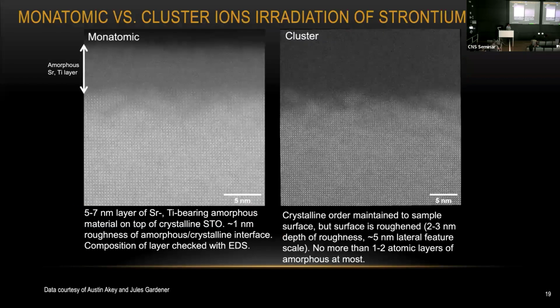And here's some data taken from my colleagues Austin and Drew. Both of them are not here today. They are working on strontium titanate, and it's a single crystal chip. The sample size is almost 1 centimeter by 1 centimeter. The main difference between these two measurements is that for one piece of sample, we did monatomic etching for 5 minutes, and for another sample we used the cluster source for another 5 minutes.